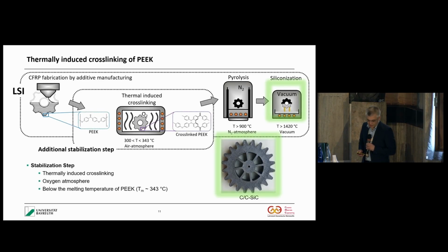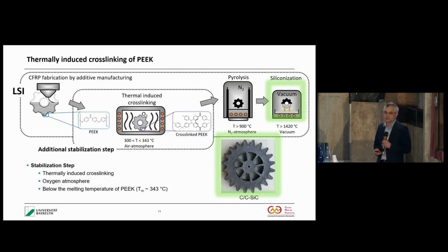Okay, so one big aspect is that if you use thermoplastics and you remelt them, or heat them up again for pyrolysis, they would remelt and you do not have form stability. So that's why you have to introduce a cross-linking step. PEEK, for example, has the interesting aspect that it reacts with oxygen below the melting temperature. That is a disadvantage if you want to join PEEK samples, for example, but it becomes an advantage for us, because it becomes a thermoset material below the melting point if you introduce oxygen into the microstructure.